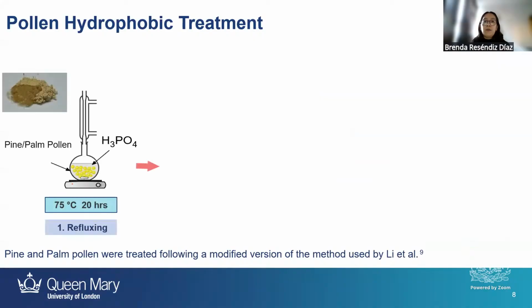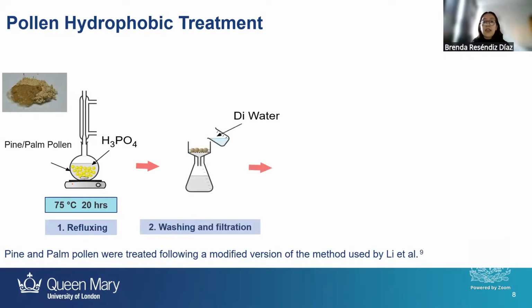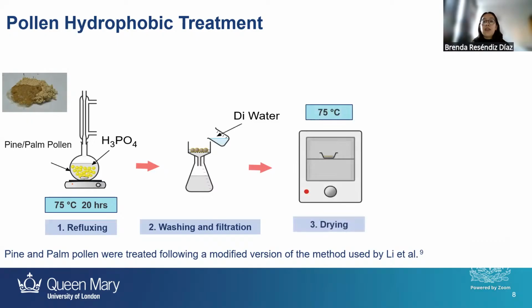So for the pollen treatment, I use phosphoric acid to remove all those proteins that I mentioned before, at 75 degrees for 20 hours in refluxing. And then I use washing and filtration with DI water, or distilled water, to remove all the excess of acid in my samples. And then I dry it at 75 degrees overnight.